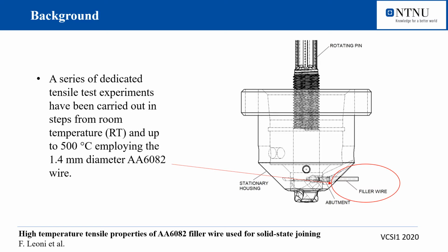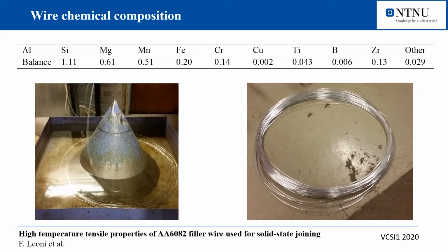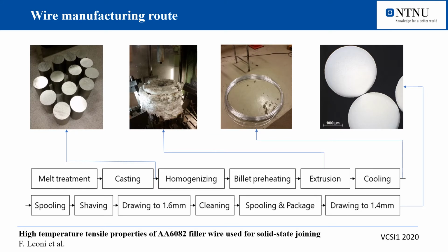The measured engineering stress strain curves serve as a basis for the analysis, and in addition, selected fracture surfaces have been analyzed using scanning electron microscopy to reveal the fracture mechanism. The chemical composition is shown in the table here, and the wire appearance is shown in the two figures. The manufacturing route of the tested wire is presented here.